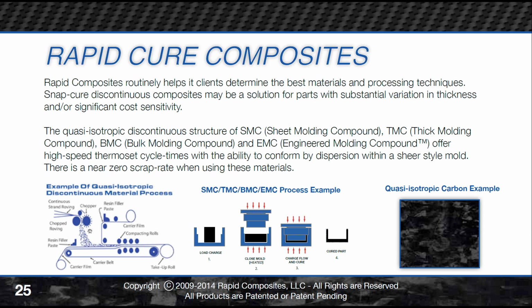So understanding that process of how that works, and that's kind of the simplistic overview of it, is very critical to understanding why the fiber is what it is. It's basically in a 2D form. Quasi-isotropic materials have more torsional and tensile stability than you will get out of a typical 2x2 type fabric material. So this is a 3D oriented fiber. So even when it's in a 2D form, it is 3D. So it's very structural. And then imagine if you put a part into a 3D form, a highly contoured hull component, let's say for a UAV or a fuselage component, it's going to be massively more torsionally stable than you're going to get out of a typical 2D 3K kind of woven type fiber.